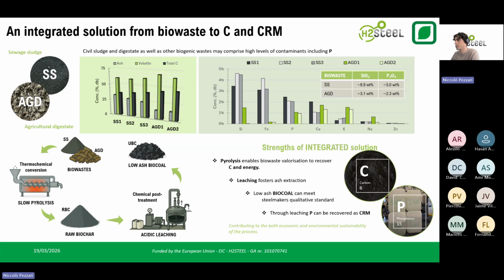These two aspects are relevant to us because the carbon is the source to produce a carbonaceous material to obtain the fossil coal substitute. But at the same time, the ashes in the material are harmful and detrimental to steelmaking practices. In particular, the alkali metals and the phosphorus do not comply with the quality requirements imposed by the steel makers.